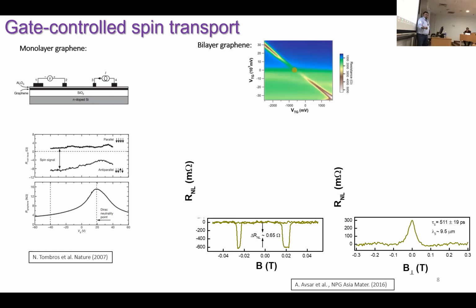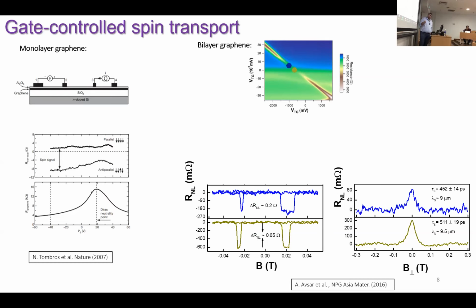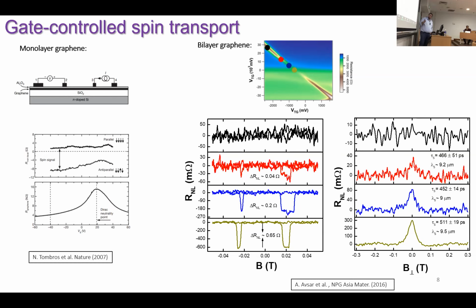Bilayer graphene is a bit different. It's not a semi-metal like monolayer graphene. If you apply a perpendicular electric field, you can induce some band gap in this material. What we were doing was measuring the spin transport as we were opening the band gap. As you open the gap, you could see that you can also control the spin current propagation in this material. But the issue is that it only works at extremely low temperatures, so it's not very practical.